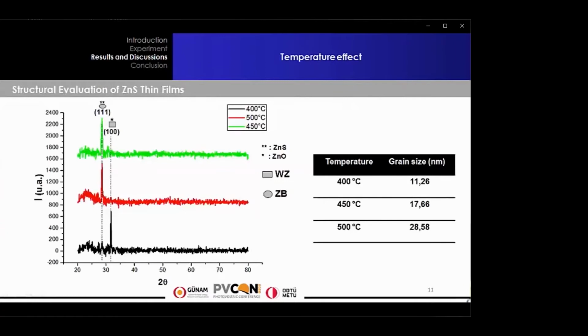In this part, we have investigated the temperature effect with a solvent of 75% methanol, 25% distilled water. The figure shows the X-ray diffraction profile of ZnS thin films grown at different temperatures from 400 to 500 degrees Celsius. Zinc blende ZnS peaks were observed for all samples grown at 450 to 500 degrees Celsius, and peaks of wurtzite ZnO were observed in the sample grown at 400 degrees Celsius. These results indicate that all ZnS samples have a zinc blende structure and that the sample grown at 400 degrees Celsius also contains a wurtzite ZnO structure.